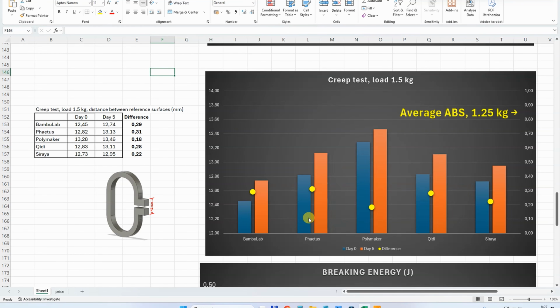Blue is the initial deformation and orange is the deformation after 5 days, and the difference between the 2 is the yellow point, that's the creeping. We can see the Polymaker had the biggest deformation, but interestingly the smallest creeping, the difference between 5 days, but all 5 materials resist creeping greatly. Just for reference, average ABS with a smaller load of 1.25 kg, which is my regular testing, would be somewhere here.